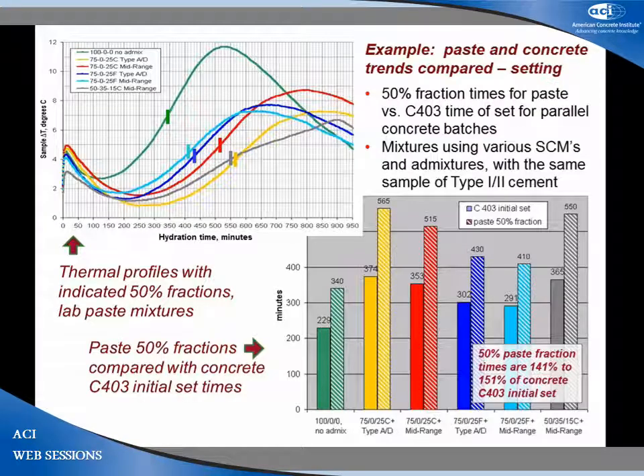Here's some actual data in that regard. We took some concrete mixtures with different suites of admixture combinations and cementitious combinations, some C-ash, some F-ash, a ternary mix with some slag and C-ash, different types of admixtures. And we put up concretes, ordinary type concretes that you would see in low-tech construction, and the C403 initial setting times for the concrete mixtures are the solid bars in each case. We took the same proportions of the paste fraction of those concrete mixtures, put them up in the laboratory, did the thermal profiles and the 50% fraction setting times, and that's the striped bar in each case. And you see that the numbers are different, but the trends are the same, and that's the important take home here.